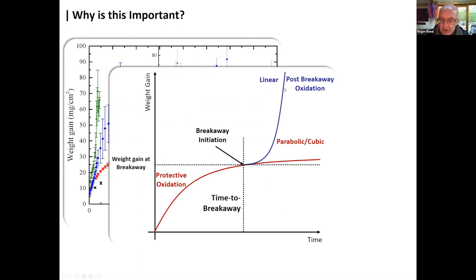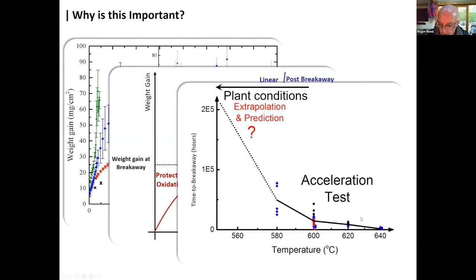And EDF Energy wanted to understand and build models for this phenomenon to allow them to make good predictions about plant safety. So this shows you schematically what they have to contend with. You do the acceleration tests maybe at 580 or 600, 620 degrees Celsius, but these are much higher temperatures than the plant is operating. And then the idea is that one would extrapolate the behavior at high temperatures to the lower temperatures to try to make good judgments scientifically and technologically about whether the plant is safe or not. So I hope that's clear to everybody.